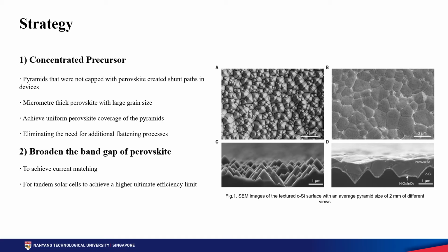It was able to achieve uniform perovskite coverage of the pyramids using this method, as we can see in the figure on the right-hand side. This eliminates the need for an additional flattening process. In addition, in order to achieve current matching, instead of reducing the thickness of a smaller bandgap perovskite, the authors broadened the bandgap of the micrometer-thick perovskite. This perovskite with a very wide bandgap, usually around 1.68 electron volts, paves the way for tandem solar cells to achieve a higher ultimate efficiency limit.